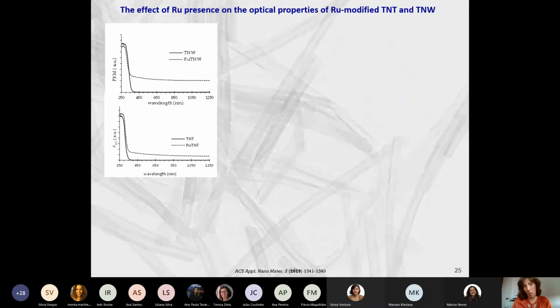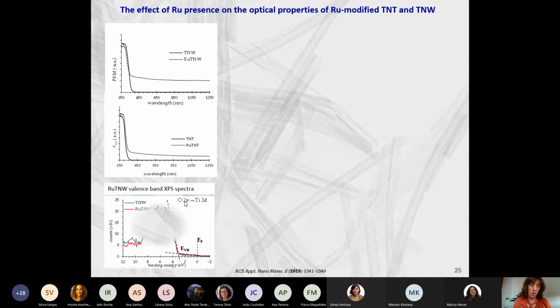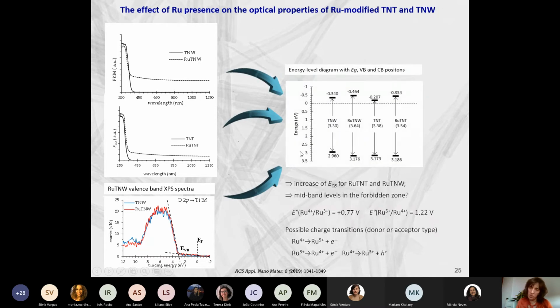But we are also very interested in the optical behavior of these samples. So these are the optical spectra of the nanowires and the nanotubes. And when we combine this information with the one coming from the valence band XPS spectra, we are able to do some calculations and then to know exactly where is the valence band and conduction band of these materials. And as you can see here, we have some shifts when we have the ruthenium in the nanowires and also in the nanotubes. We have an increase for negative values, of course, here in the conduction band, and the same for the valence band position.